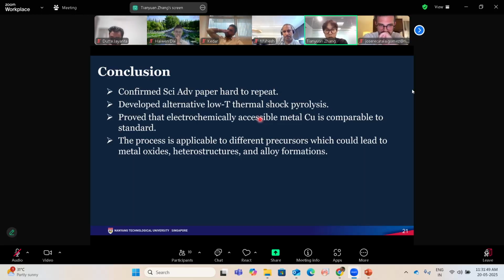And the result proved that the electrochemically accessible metal copper is comparable to the standard samples, as the CV showed before. And our OpenTrons process is applicable to different precursors, for example, different copper salt, nickel salt, or silver salt, which could lead to different metal oxide heterostructures and alloy formations. And that's all my presentation.